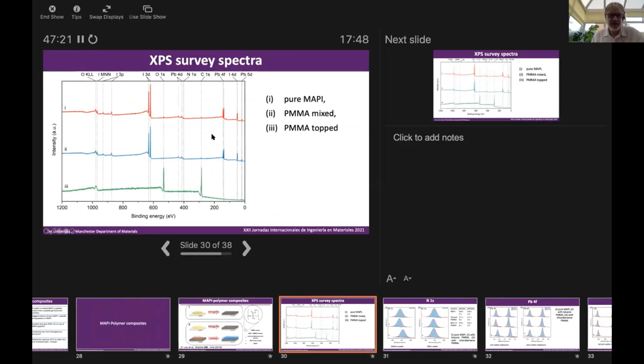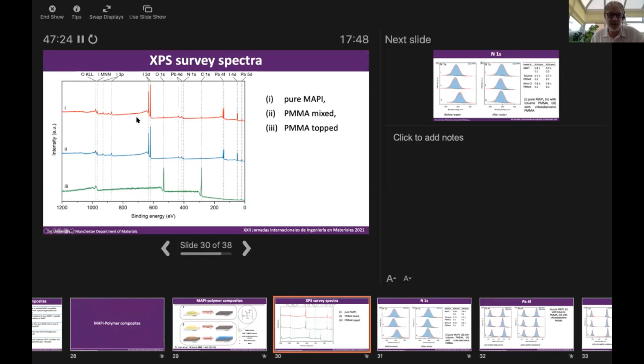These are the survey spectra that we get. For the pure MAPI, we obviously see iodine, lead, nitrogen. For the blend, where we mix the two things and then spin coat them together, again, we can see all of the peaks you would expect: the iodine, the lead 4D, lead 4F. But for the PMMA topped sample, we don't see any of the MAPI. That's because this PMMA topping must be around 10 nanometers thick or more, so we can no longer see the perovskite below the surface. So normal XPS wasn't much use for this particular one.